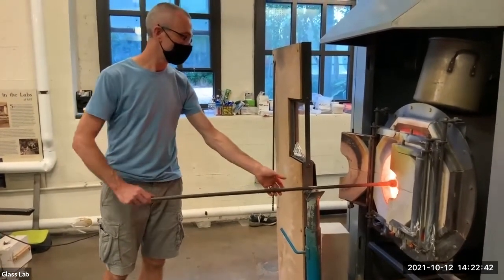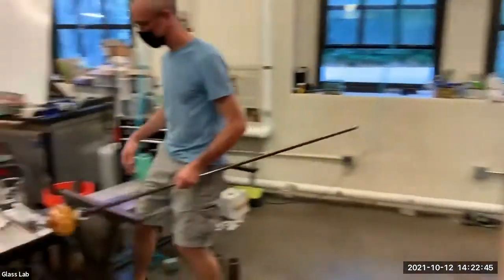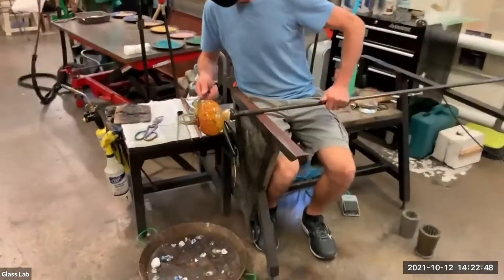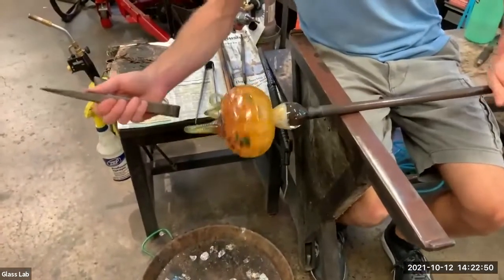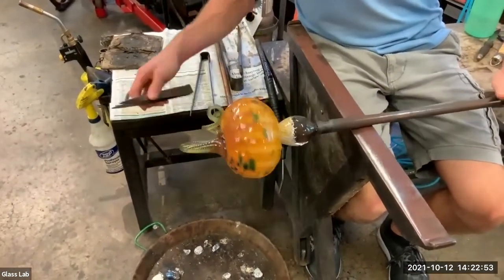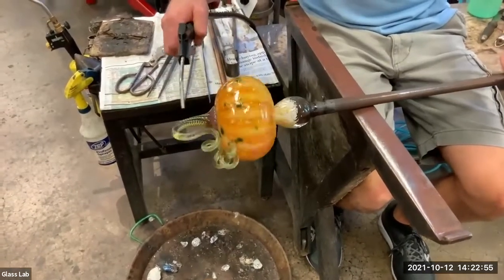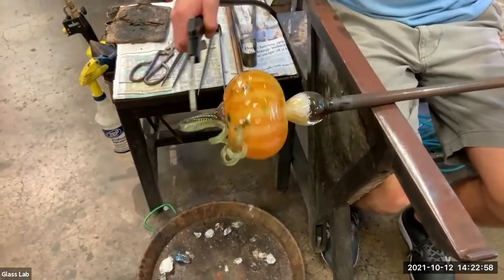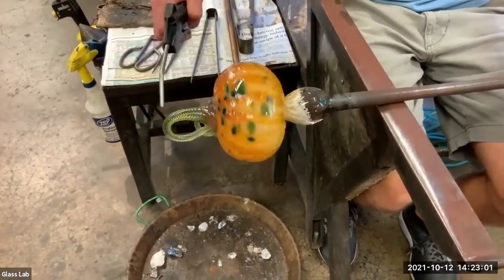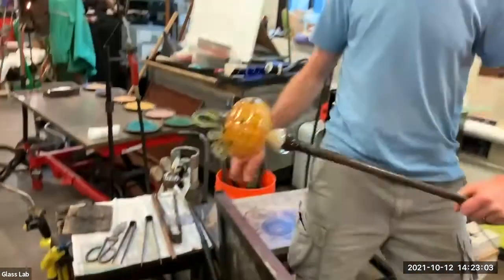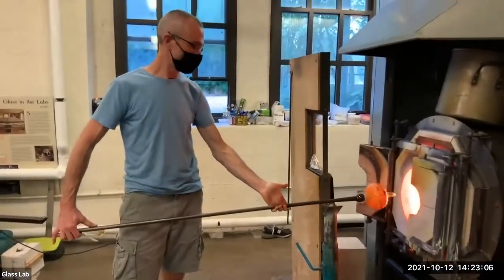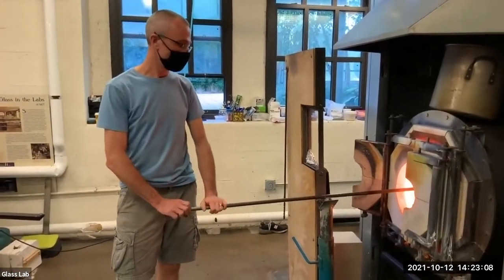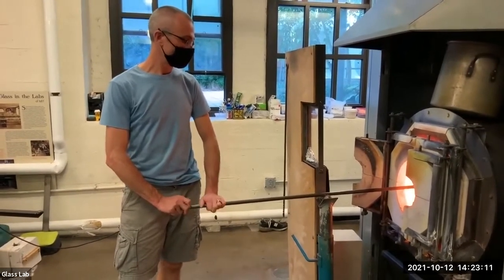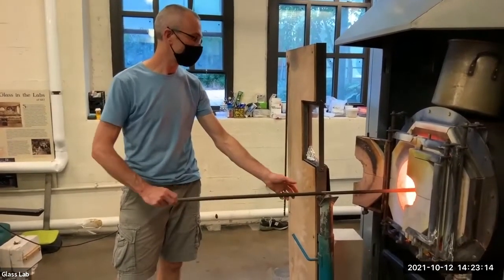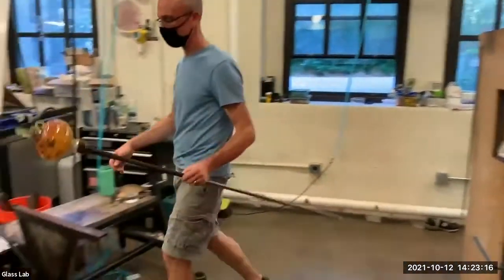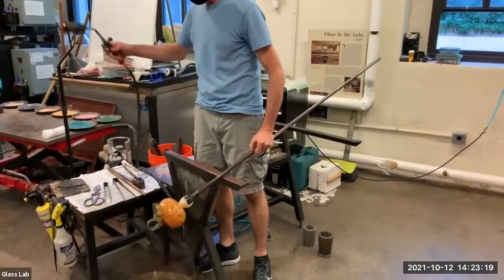So you cannot let this pumpkin just cool down to room temperature as fast as it can, because it will thermally shock. Glass really does not like to cool down fast because the inside and the outside cool at such different rates. So we will have to put this pumpkin into an oven where it holds at 930 degrees until we're finished working. And then we'll send the oven down on a very slow program overnight. So it loses heat over about 8 hours. And then in the morning, it should be happy.